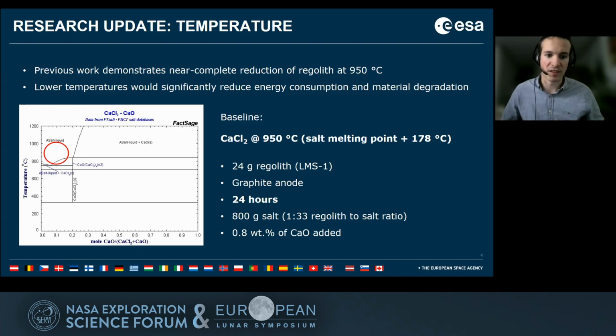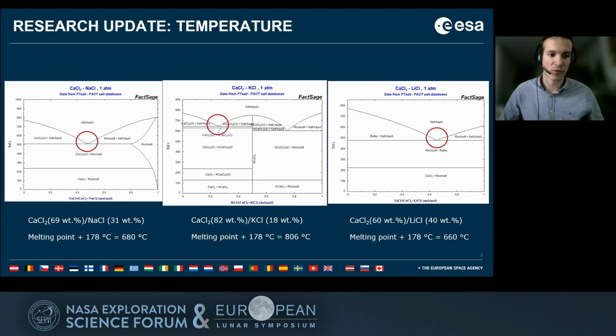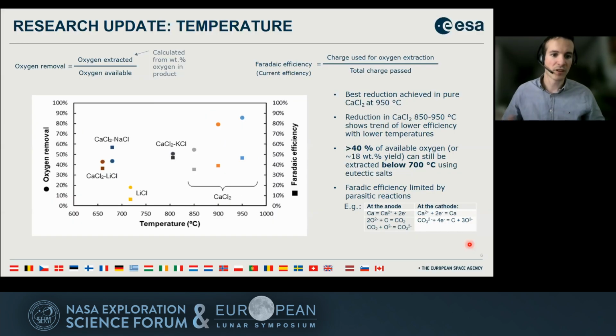The baseline is also at 950. So what we changed is that we tried to find a way to lower the melting point. Since the melting point of calcium chloride is 770 degrees, you can already get some margin here, but otherwise, if you want to go lower, you need to mix the salt with different ones. That's why you have eutectic points when you mix calcium chloride with sodium chloride, potassium chloride, or lithium chloride. So we now have different temperatures where we can run, at 680 degrees, 806, and 660 degrees, which was the lowest temperature we tried with these different techniques. The results we got are in this table.